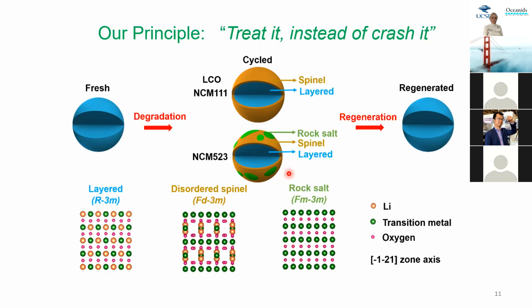So what we are doing here is, by understanding this process, we are going to design a so-called regeneration process so we can reverse, okay, we can rejuvenate this surface phase, this orange phase and this green phase, back into this well-ordered blue phase, okay, again, back to layered structure. So this is what we're doing. So we are making a lot of efforts after understanding this process to try to regenerate these degraded particles into regenerated particles, which will have exactly the same properties as your old materials.